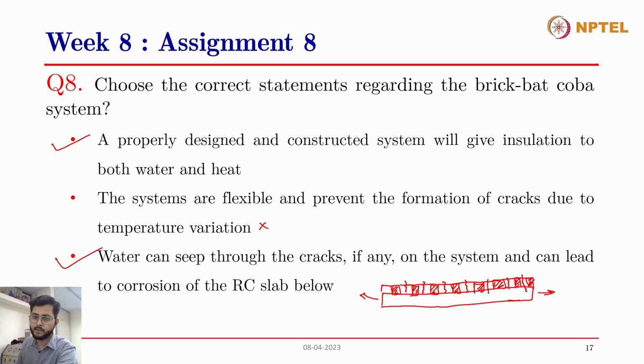These are the cracks. The cracks will be formed between the brick layers, and when these cracks are formed, once there is rain, water can get inside these cracks. And since these are bricks, bricks have a good water retention. They can absorb a lot of water, as Dr. Satish has also mentioned. They can absorb and retain a lot of water, and they will act as a water sink. And this retained water can seep inside the concrete surface beneath the brick bat koba layer, and they can affect the steel reinforcement in the slab.